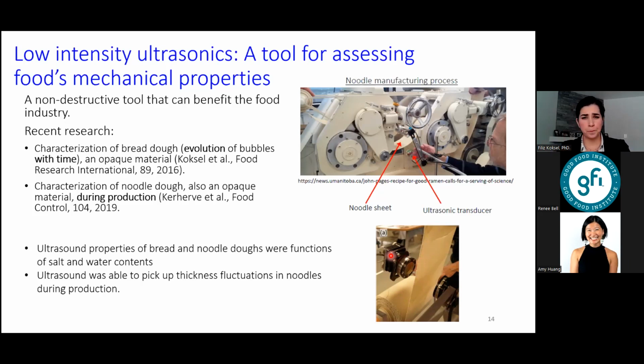And the outcomes of these initial studies was that using low intensity ultrasonics, we were able to detect changes in product properties, changes in bread and noodle properties as a function of ingredients. For example, if you increase or decrease salt content, if you increase or decrease water content, you can get that information extracted from the changes in the ultrasonic signal.